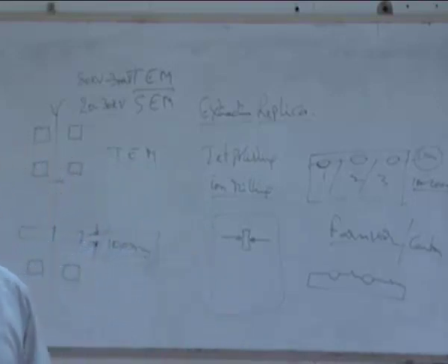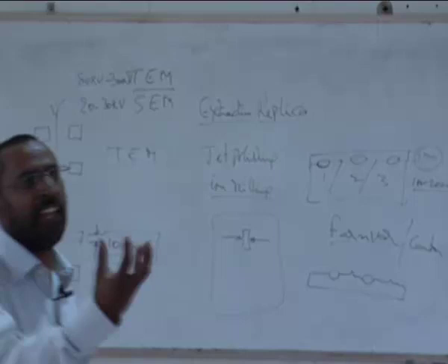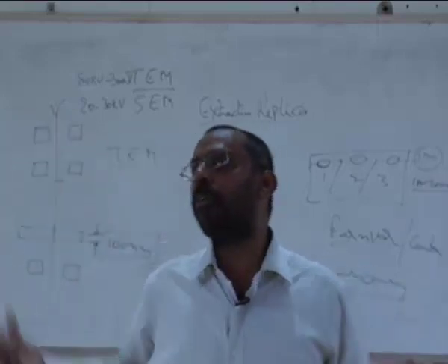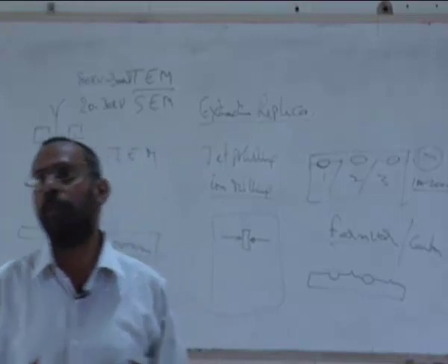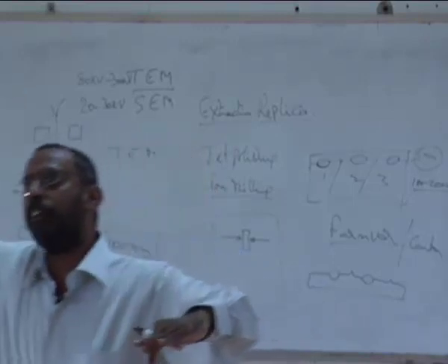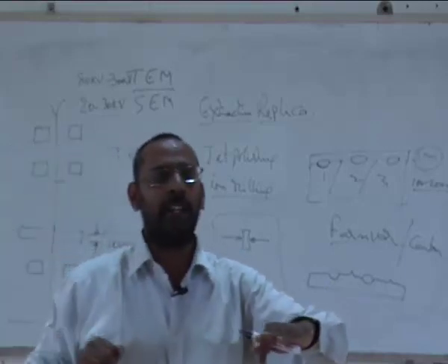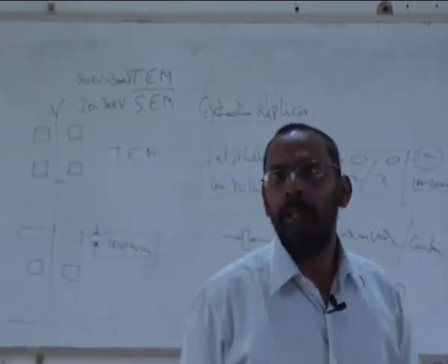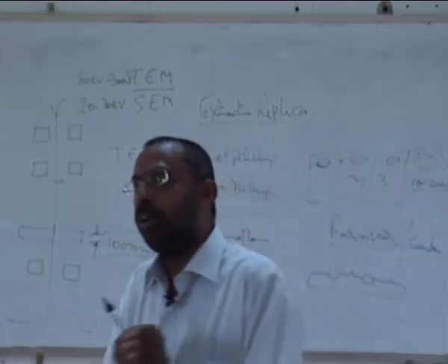These microscopes are not only microscopes to give you information on sizes, shapes and size distribution of particles, but you can also use the electron beam like an X-ray beam to get a diffraction pattern. That's what we are going to jump into in the next few minutes. I can put this electron beam on this particle, get a diffraction pattern, and analyze it to know the crystal structure. I know that theta double prime, theta prime and theta have the same crystal structure, but their lattice parameters are different.